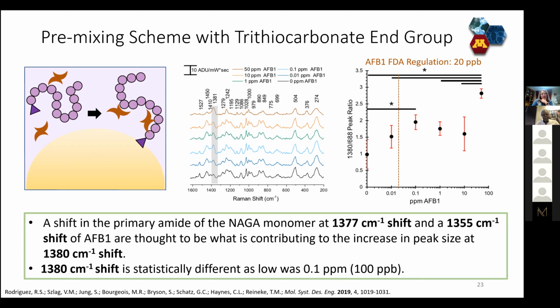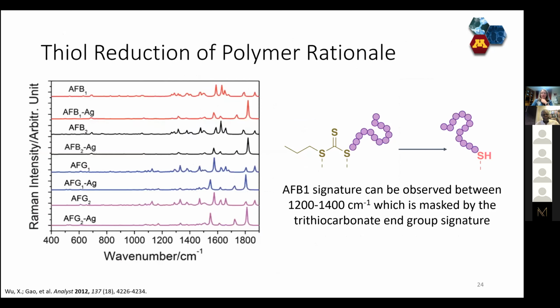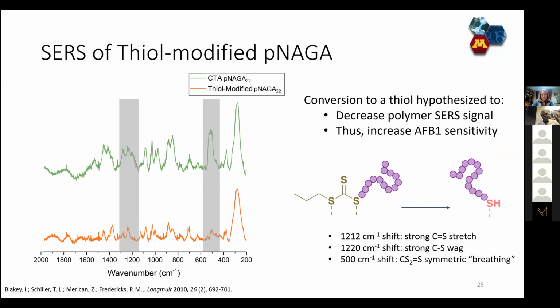So we were concerned that the trithiocarbonate end group was kind of making it harder to do the detection. When you have more bonds, of course, you have more vibrations, which means you have more Raman modes. And so we were worrying that that was blocking some of what we were looking for. So here you can see that some of the peaks for aflatoxin we're going to be looking at are in this 1200 to 1400 wave number shift region. And that's where a lot of the trithiocarbonate bands are. So we did a chemical reaction and converted our polymer from a trithiocarbonate termination to just a thiol, which is much simpler, still sticks to gold really nicely. And when we took that polymer, I can show you the Raman spectra comparing them.